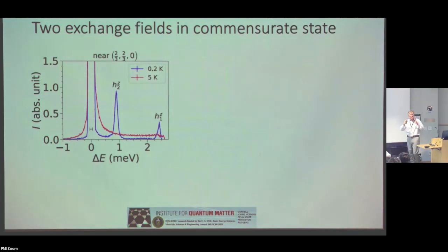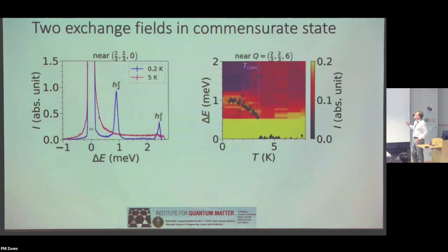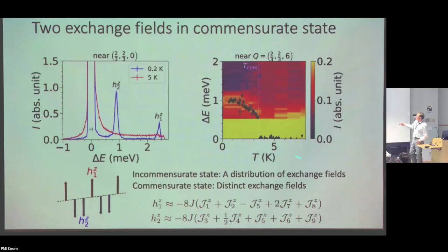So in a sense, this is a way of very accurately knowing that you have an incommensurate structure, because I have this whole continuum of exchange fields that have split the doublets. But then when I go into the commensurate structure, I just get two specific energies coming out. So now I have just two specific sites. It's really quite nice. And so this is the picture that happens in the incommensurate state. Many different continuum of different environments are found. But in the commensurate state, then I have one upspin, two downspins, and those have different environments.